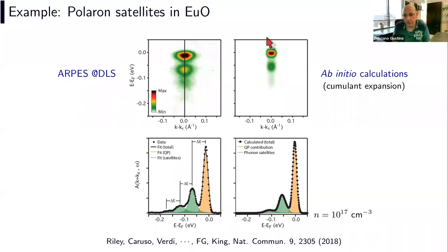In the calculation also, if we draw a line in the middle here, we find a quasi-particle peak, satellite, and so on. So this is just a way to say that, yes, one can confirm that the satellites are an effect of electron-phonon interactions, and in particular, of an interaction with a specific polar optical phonon, that is the longitudinal optical mode. So that's to give you an idea of the level of accuracy one can achieve now with this kind of